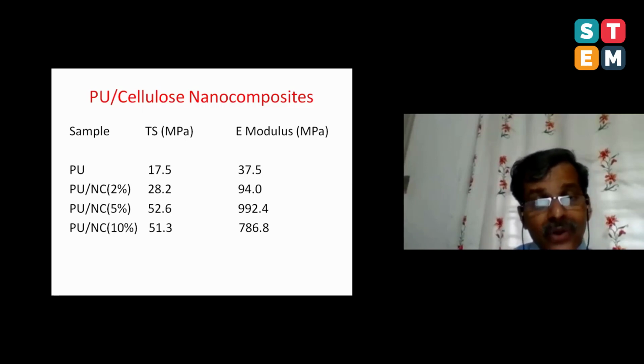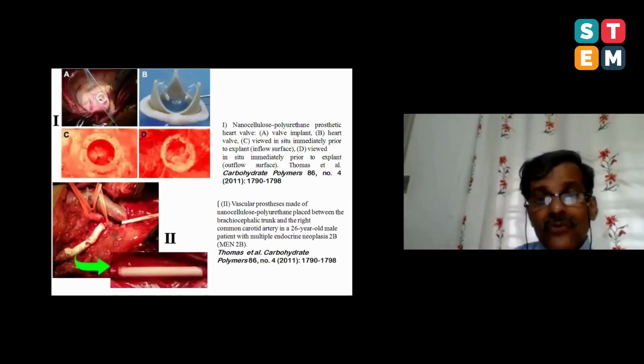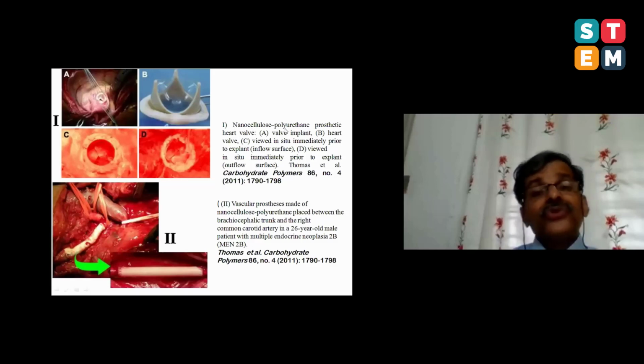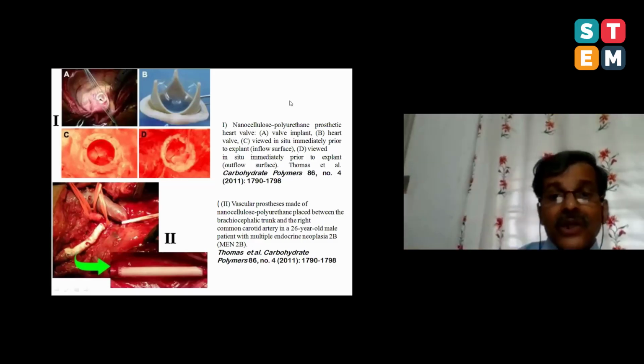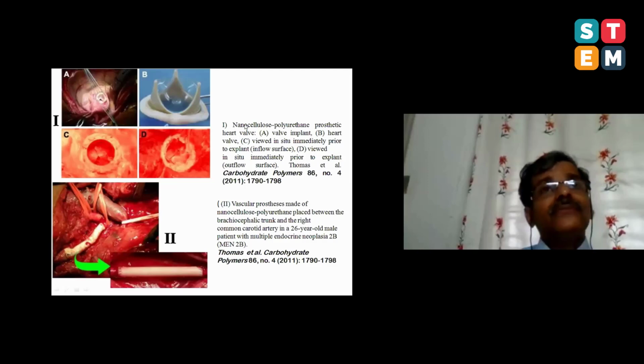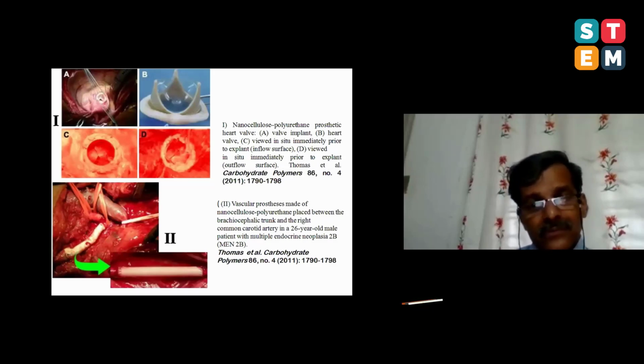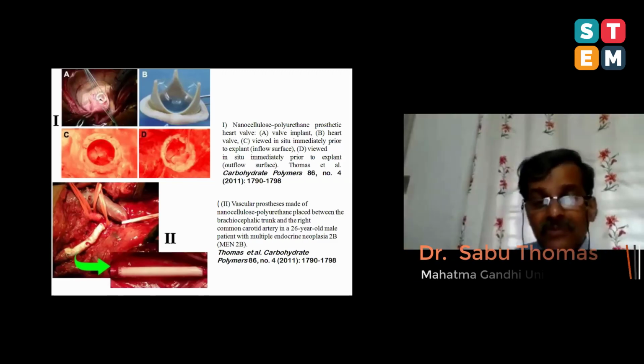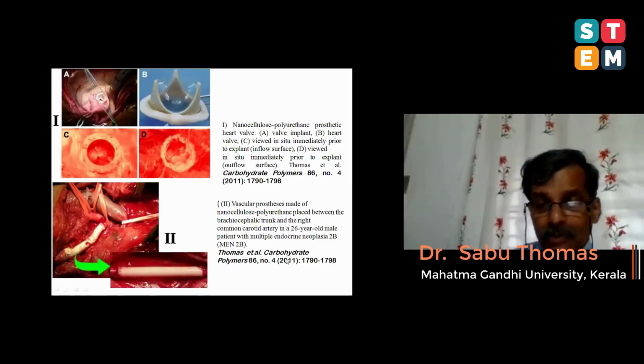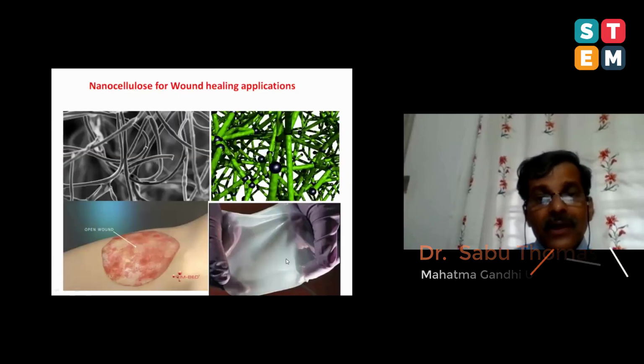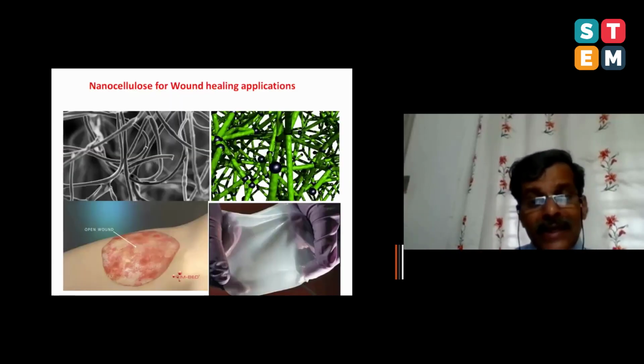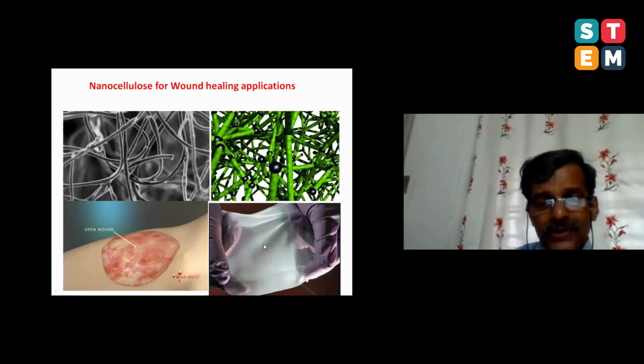So what my Brazilian colleague did is, with the support of a hospital, we made a nanocellulose polyurethane prosthetic heart valve. Look at nanocellulose extracted from pineapple waste. We transformed this into a beautiful prosthetic heart valve. The Brazilian group and I have lots of patents, and we published this. Those really interested can look at our Carbohydrate Polymers paper. This is an exciting material for wound healing applications. You can see our nanocellulose, extremely porous, on an open wound, and this wound could be closed by this nanocellulose.